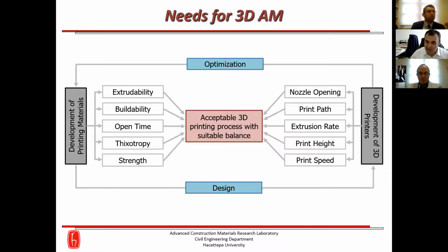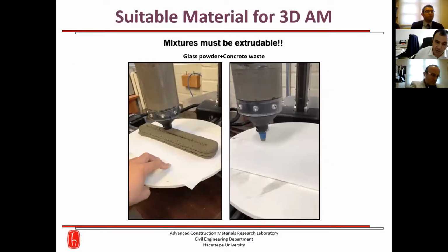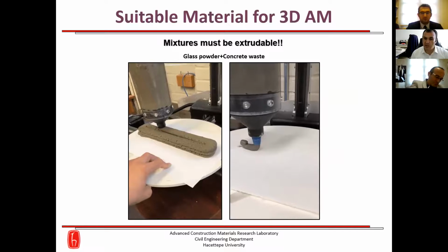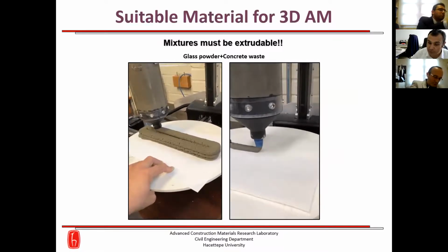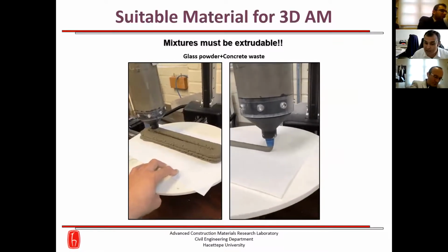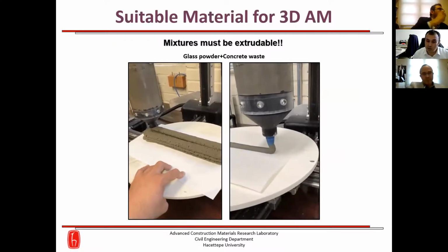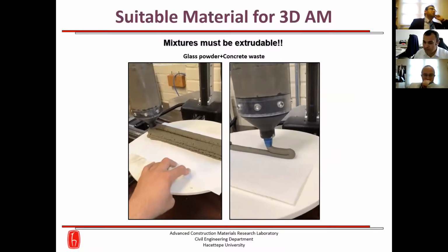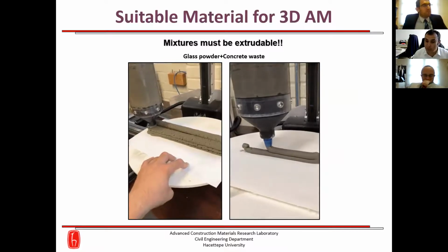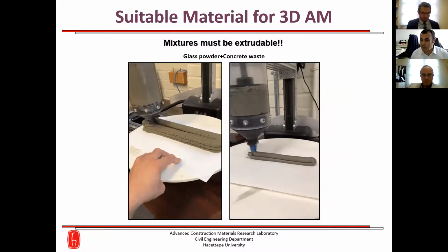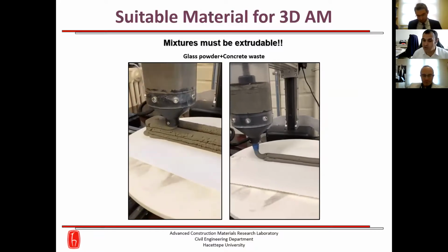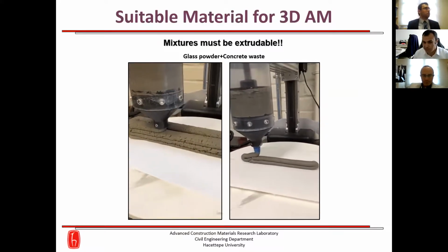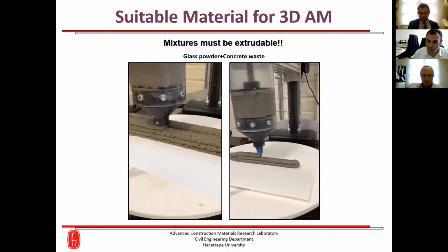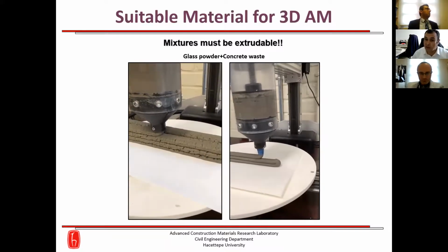There are several challenges that need to be solved before developing materials which are suitable for 3D printing concrete. For example, the materials in the fresh state, in terms of 3D additive manufacturing, require some properties. One of them is extrudability. Extrudability is defined as the quick and reliable transferability of the material with low energy consumption from the storage bin through the printing holes and the nozzle without any blockage and segregation. In addition, the extruded filaments must be continuous, smooth, and without cracking.